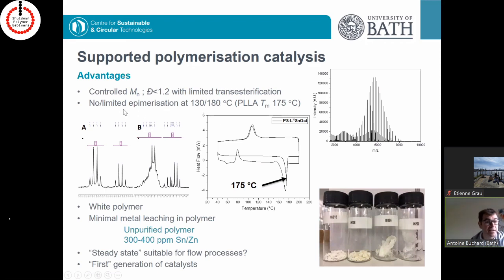A good point as well is that there's no or limited epimerization, and this was confirmed by the melting point of the PLLA, for example, that we produce, which is quite high. And if you're looking at the NMR, for the most specialist of you, this is something that's produced with our beads under melt conditions, whereas this is something produced by DMAP, a typical organocatalyst that you can use for the ring-opening polymerization of lactide. We do produce the white polymer, which is not negligible. There's still minimal metal leaching in the polymer. Even on the unpurified polymer, we only have 300 to 400 ppm at the type of loadings we're using.